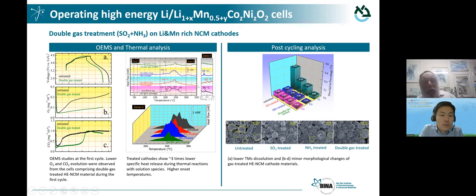We use differential scanning calorimetry. And here again, if you compare our favorite material, the heat evolution is much lower compared to the reference and also to the other samples that were treated with only one gas. The onset also is higher when we talk about our favorite. We measure the dissolution of transition metal. Whenever we have a cathode comprising lithiated transition metal oxide, we have a problem of transition metal cation dissolution. They go to the negative and they destroy the passivation of the negative, and we have terrible crosstalk between the negative and the positive electrode.